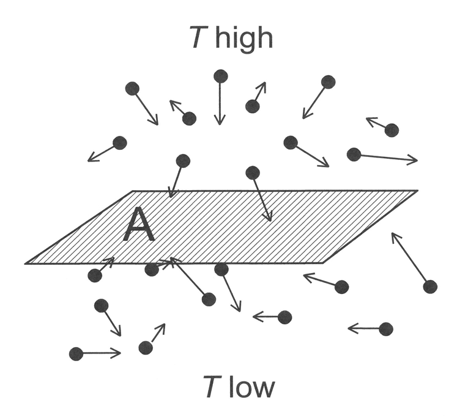In metals, thermal conductivity approximately tracks electrical conductivity according to the Wiedemann-Franz law, as freely moving valence electrons transfer not only electric current but also heat energy. However, the general correlation between electrical and thermal conductance does not hold for other materials, due to the increased importance of phonon carriers for heat in nonmetals. Highly electrically conductive silver is less thermally conductive than diamond, which is an electrical insulator, but due to its orderly array of atoms it is conductive of heat via phonons.